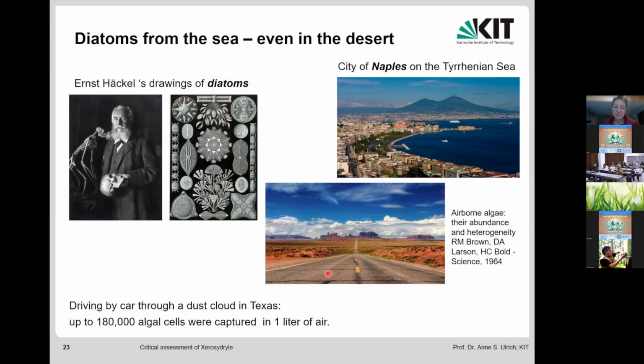And in fact, a study that we found from 1964 was that in Texas, dust was collected, and in 1 liter of air, 180,000 diatoms were found, even in the middle of the desert. So diatoms are everywhere. You cannot avoid them when you work in open labs, and even under the clean bench, they find their way into your sample if you're not extremely careful.